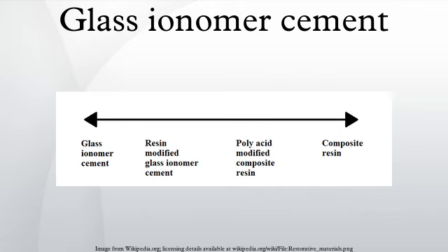The resin-modified materials have been shown to have significantly higher flexural and tensile strengths and lower modulus of elasticity than the conventional materials. They are therefore more fracture resistant but their wear resistance has not been much improved. In addition, their strength properties are still much inferior to those of composite resins, and so should not be subject to undue occlusal load unless they are well supported by surrounding tooth structure.